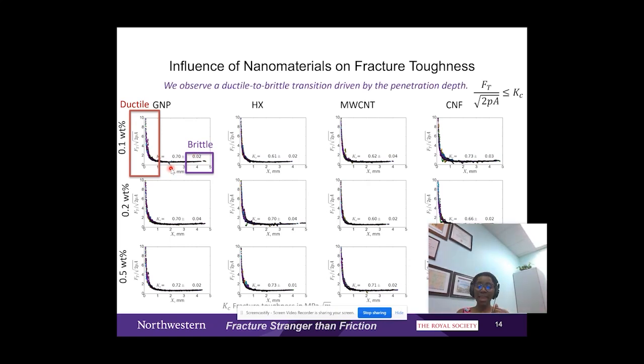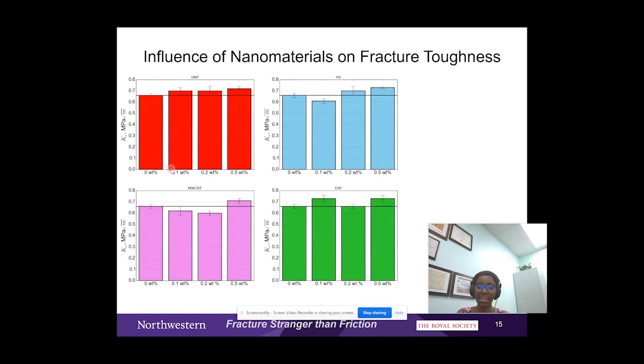Then I try to see what is the influence of both the type of nanomaterial and their volume fraction on the fracture toughness. Now, for graphene nanoplatelets, I observe always an improvement in the fracture toughness when we add graphene nanoplatelets. Similarly, for carbon nanofibers, there's always an improvement. However, in the case of helical carbon nanotube and multiwall carbon nanotube, there are some volume fractions where we observe a slight decrease, a really small decrease, and that suggests that there's some room to optimize our dispersion process.